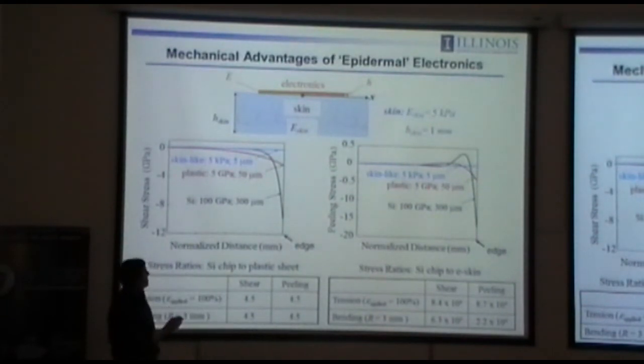And you can think about the magnitude of those stresses for different parameters associated with electronics, in particular the Young's modulus and the thickness. And you can compute those stresses as a function of position, starting from the edge of the piece of electronics out to its center. And this is what you end up seeing here. So these are the shear stresses here, peeling stresses, as a function of normalized distance away from the edge. So the edge is sitting over here.